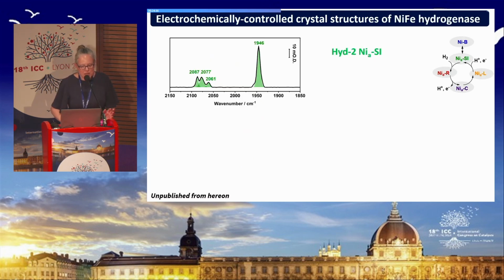So we start with the nickel Si state at the beginning of the catalytic cycle. And what we've done here is used our electrochemical approach to dial up conditions that give us a very pure nickel Si state. We then extract crystals from that poised solution and determine the X-ray diffraction structure of those. There were a lot of reasons why this might not have worked.